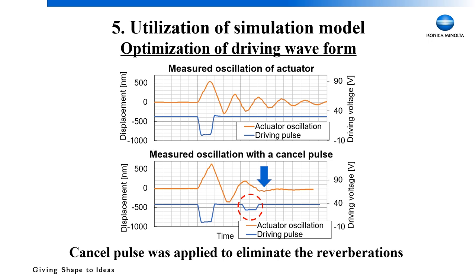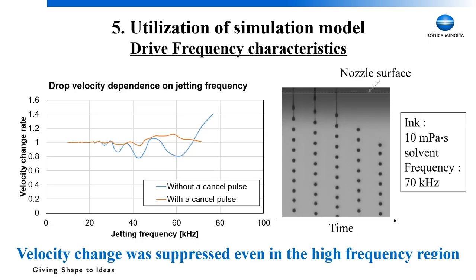By using the optimized waveform, velocity change was suppressed even in the high frequency region. And we succeeded in ejecting droplets at 70 kHz stably.